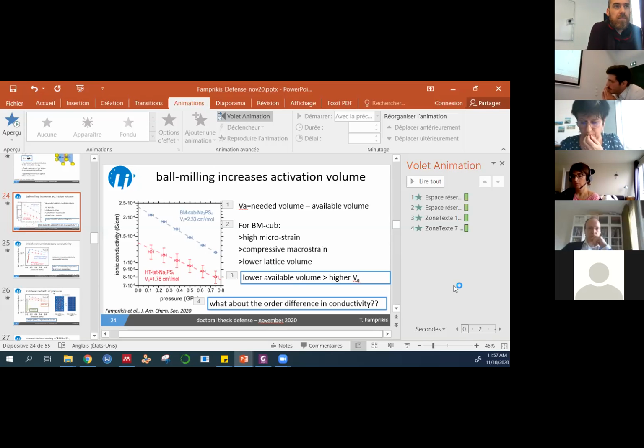My feeling, so I have not performed an accurate Rietveld on these materials. I mean the aqueous ones, not in general. For the aqueous one, it's simply a profile fit that I identify as Na3PS4. I agree there is the possibility of stoichiometry in Na3PS4, but I do not think that structurally it would be as easy as what I propose for Li3PS4 because of their distinctly different structures. Li3PS4, I think of it definitely as made from a close packing of the sulfide ions, and then you can fit whatever you want in them. So you can play with the composition of lithium versus phosphorus, and you have a lot of space and a lot of empty sites to do so.